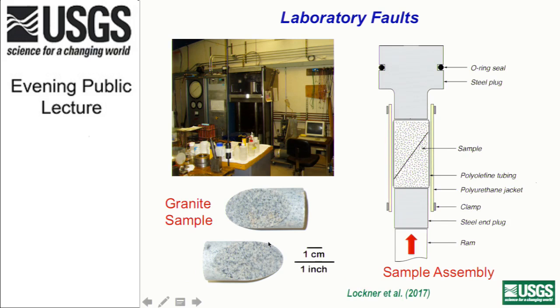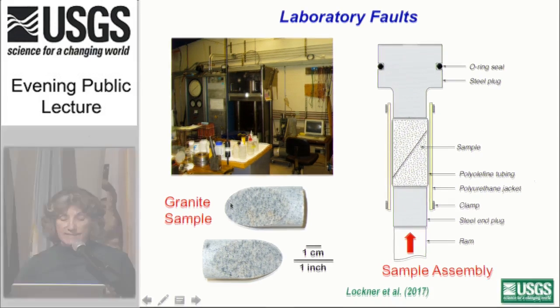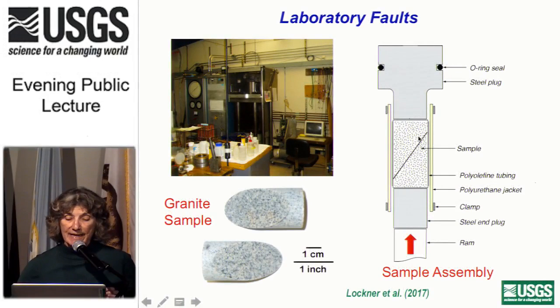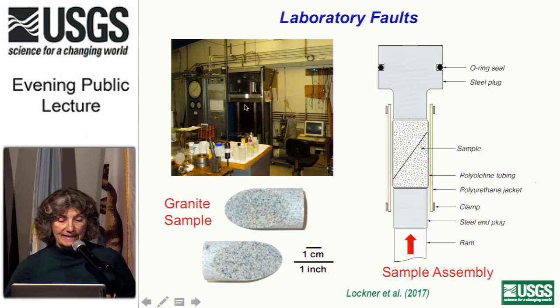It used granite cylinders that we were testing. They're 1 inch in diameter, and they were cut into two pieces along a diagonal saw cut, so it creates a fault, a laboratory fault zone. So in the experiments, the sample is placed in a jacketing material and other parts of the sample assembly. It's placed in a pressure vessel, like this one here, and then during the experiment, we apply a confining pressure, and then for these shearing tests, a ram advances against the base of the sample assembly and it causes slip along the fault plane here.